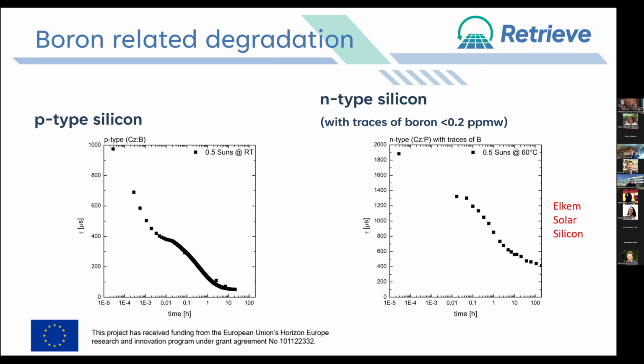So the message is, purification is needed. And the way we see it, boron is the problem. In the regular p-type silicon containing boron, we see a degradation of the lifetime when the wafer and the cell is first illuminated. We have light-induced degradation. The lifetime can be reduced by 90% of the initial minority carrier lifetime in the wafer. And that is something you will notice on cell and module performance as well. And unfortunately, if you have n-type silicon with traces of boron, you will see the same degradation. It's not as large, but this degradation is quite detrimental if you're trying to make an n-type solar cell out of materials containing even a little bit of boron.